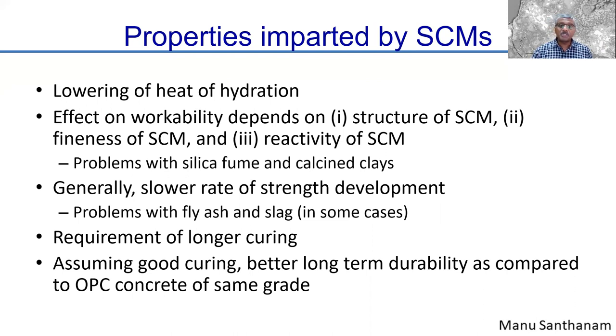Workability, of course, can be changed or can be adversely affected depending upon the type of supplementary material that you have. The structure of the SCM, the fineness and the reactivity can lead to different effects as far as workability is concerned. Generally, silica fume or calcined clays can give you problems of workability, whereas fly ash gives you an enhancement of the workability and slag does not really affect it significantly.